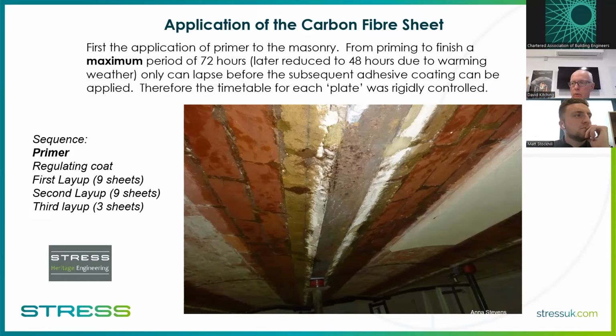You need that uniform surface. So what you will notice if you put a straight edge up, even to that brickwork, is that little bits of mortar stick out, bricks at a slightly different angle to another one. And if you applied the carbon fibre sheet to that brickwork, you'll end up with little air holes, little areas that aren't fully bonded. And of course, if you're not fully bonding the whole area, you're reducing the capacity of the carbon fibre to do the job. Therefore, it's really important to make sure you've got 100% bond from brickwork to carbon fibre.